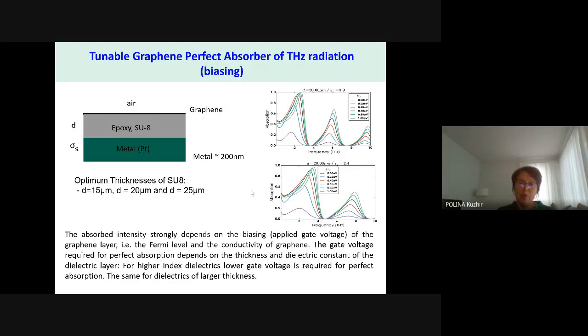Here I present the results collected for graphene put on a thin dielectric slab on top of a reflector, with radiation coming from the graphene side. Through constructive interference, you can achieve either perfect reflection or perfect absorption, and we are interested in perfect absorption. To tune the position of this absorption peak, you just need to bias graphene.